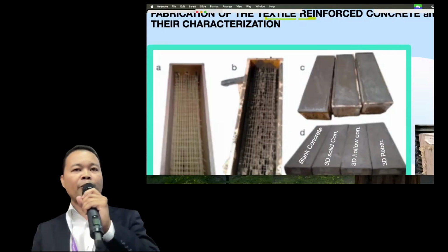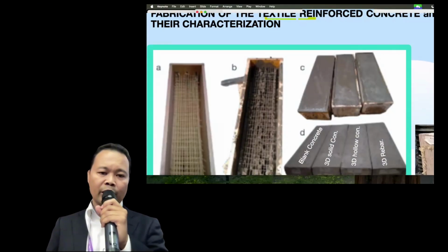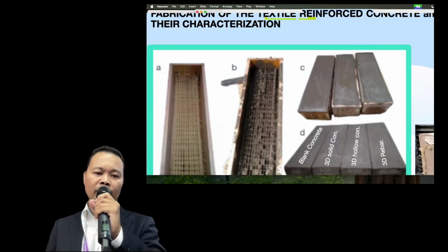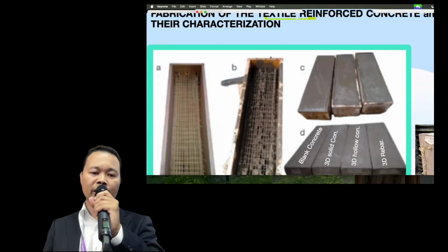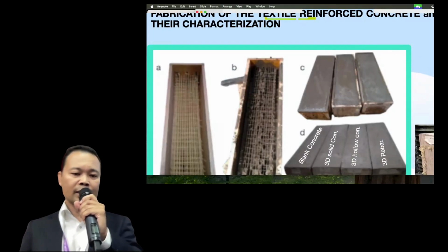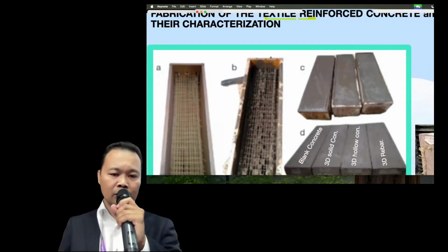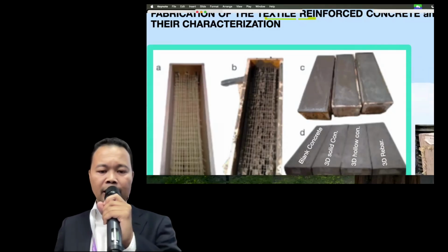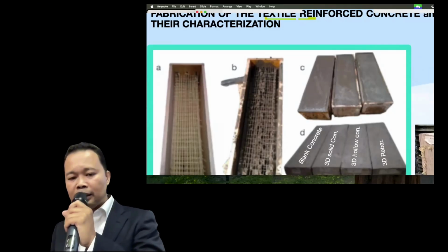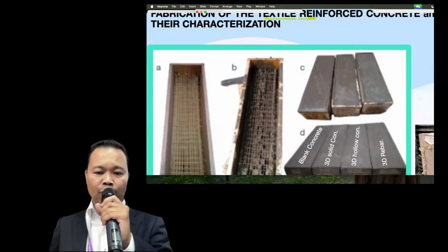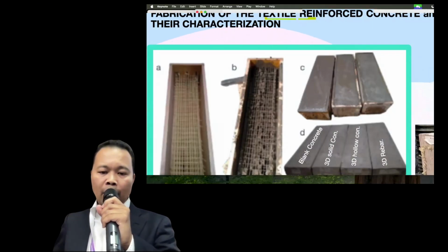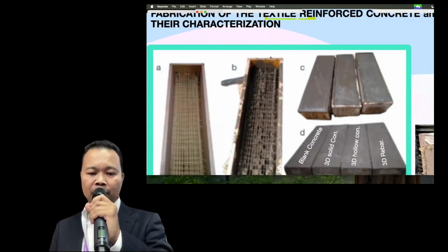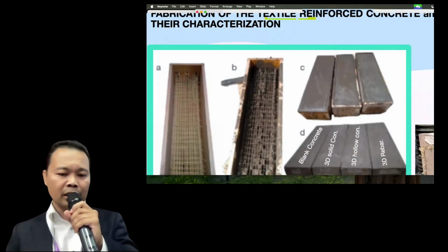And then we prepare the cement. Usually we use cement mortar, and then we use sand, small stone, water, and hardener, and mix them together. And then we pour this cement as a matrix into the mold like this, and after 10 days we remove the mold, and then we prepare the samples, and also we prepare the blank concrete.